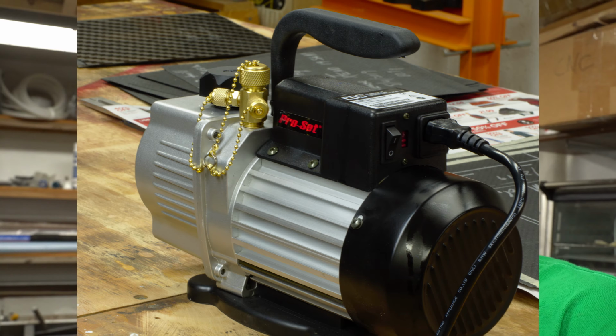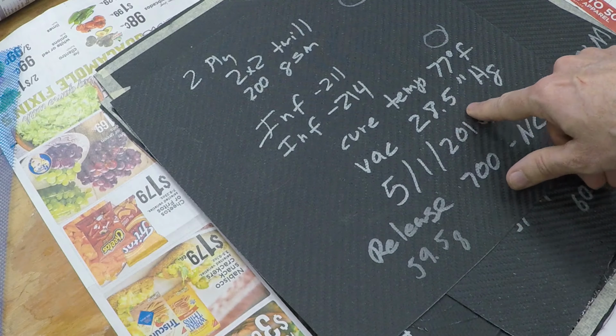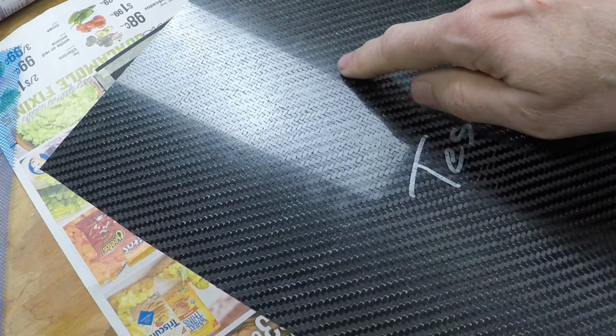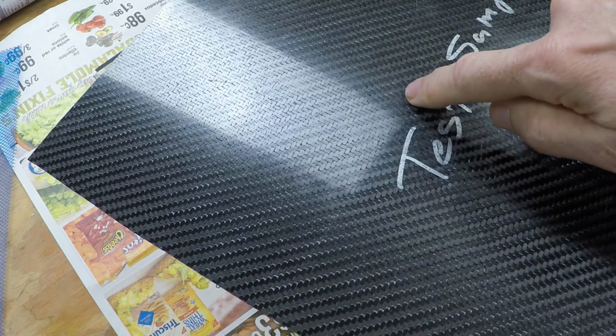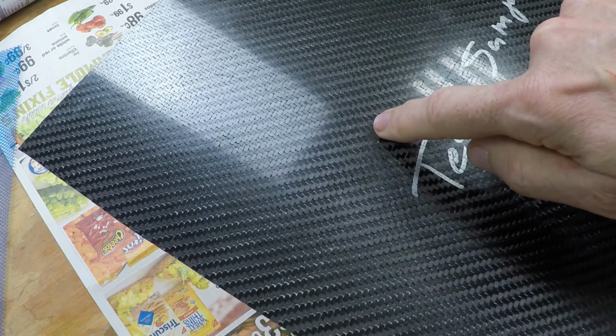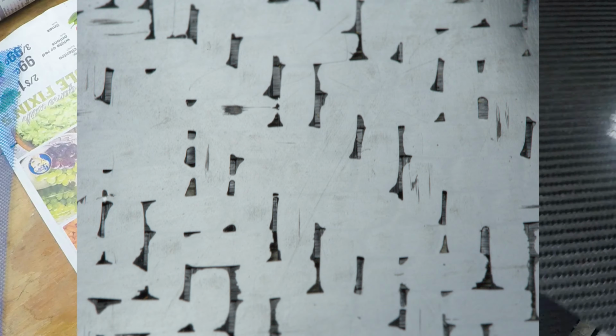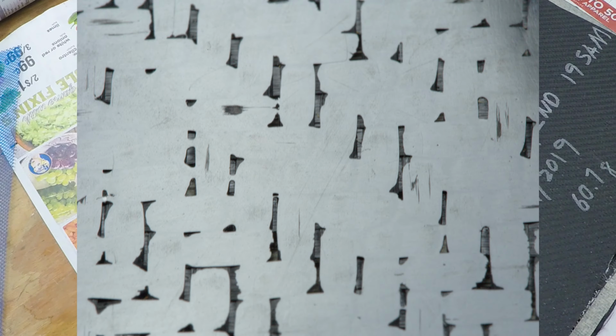Another suggestion I had in comments was I wasn't using enough vacuum. The vacuum pump I had been using could only pull 25.5 inches of mercury of vacuum. So I broke down and I got a vacuum that could pull 28.5. And so I did a test with that. And again, it did not fill the crimps, although it came much closer. There were small areas where the crimps were filled. So it helped, but it wasn't sufficient, but it was very, very close.